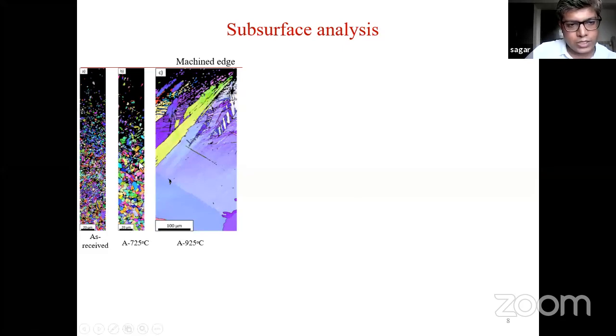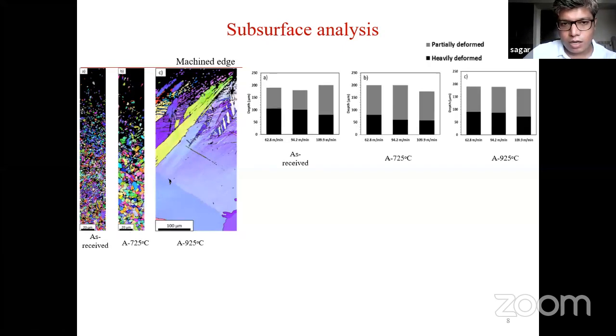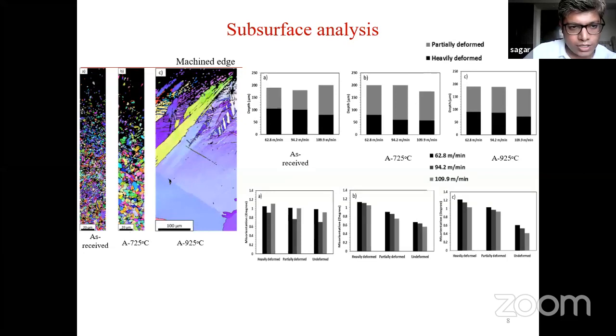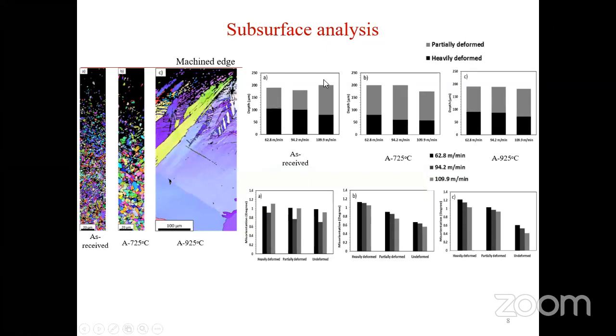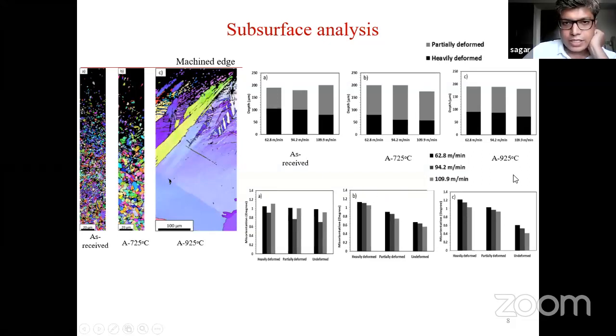With as received and annealed 725 degrees Celsius, we could not see much of those things because the highly distorted structure has formed. But by this distorted structure, we could see how much is the machining affected zone, meaning due to machining, how much distortion happened at subsurface level. There you could see, at subsurface level, when you increase the grain size, the depth of machining penetration has been reduced for every cutting speed.